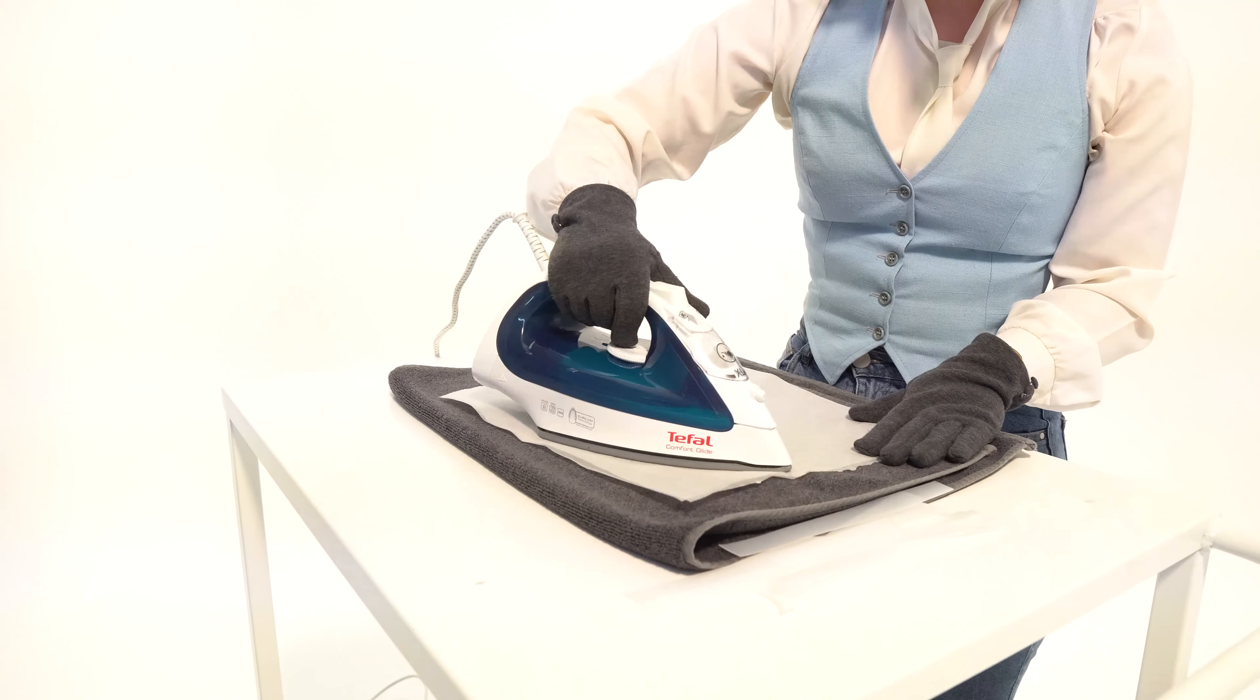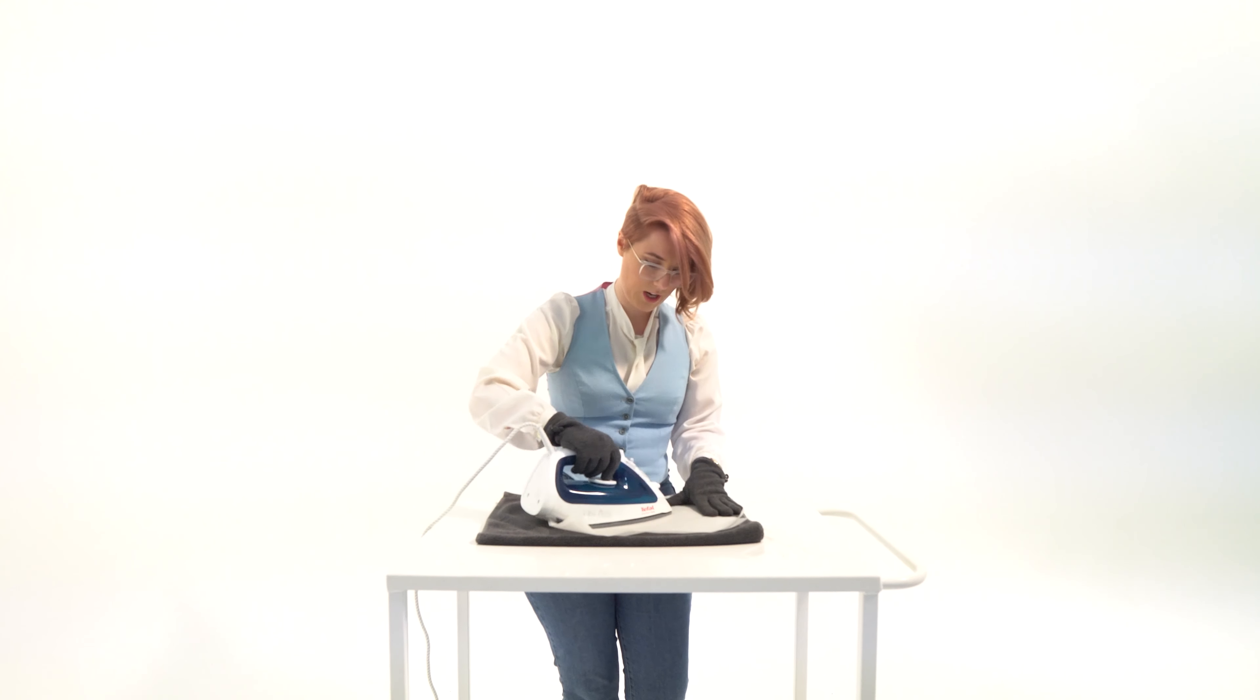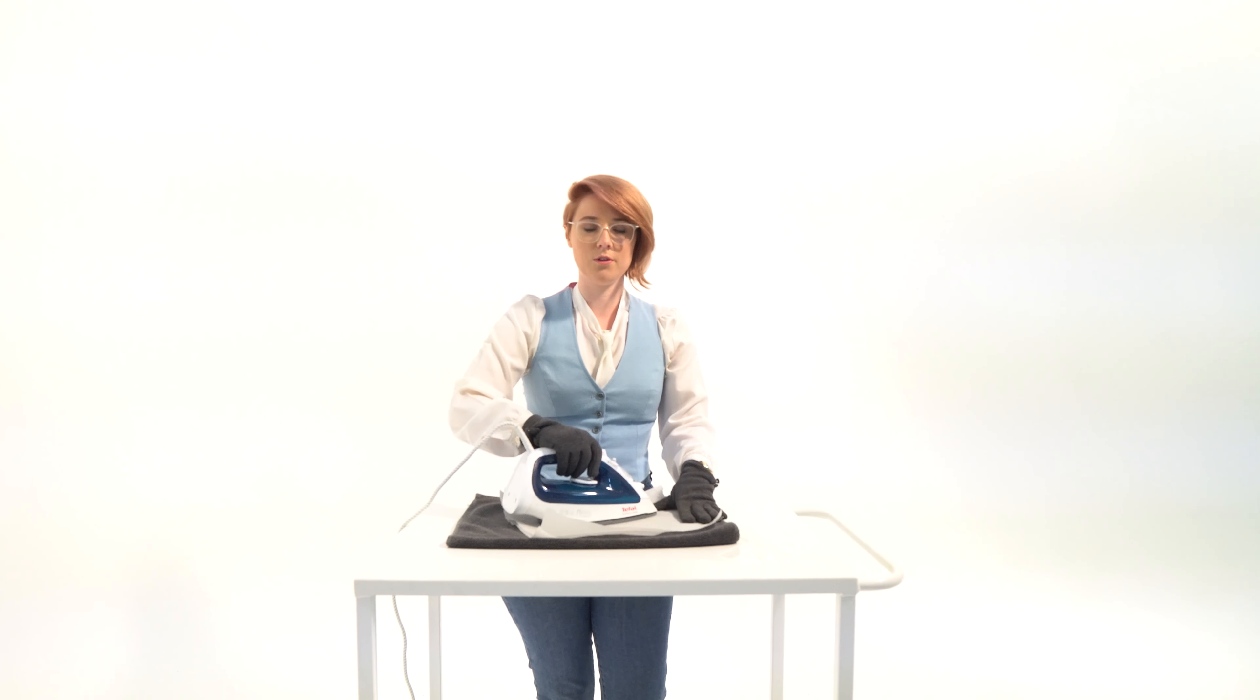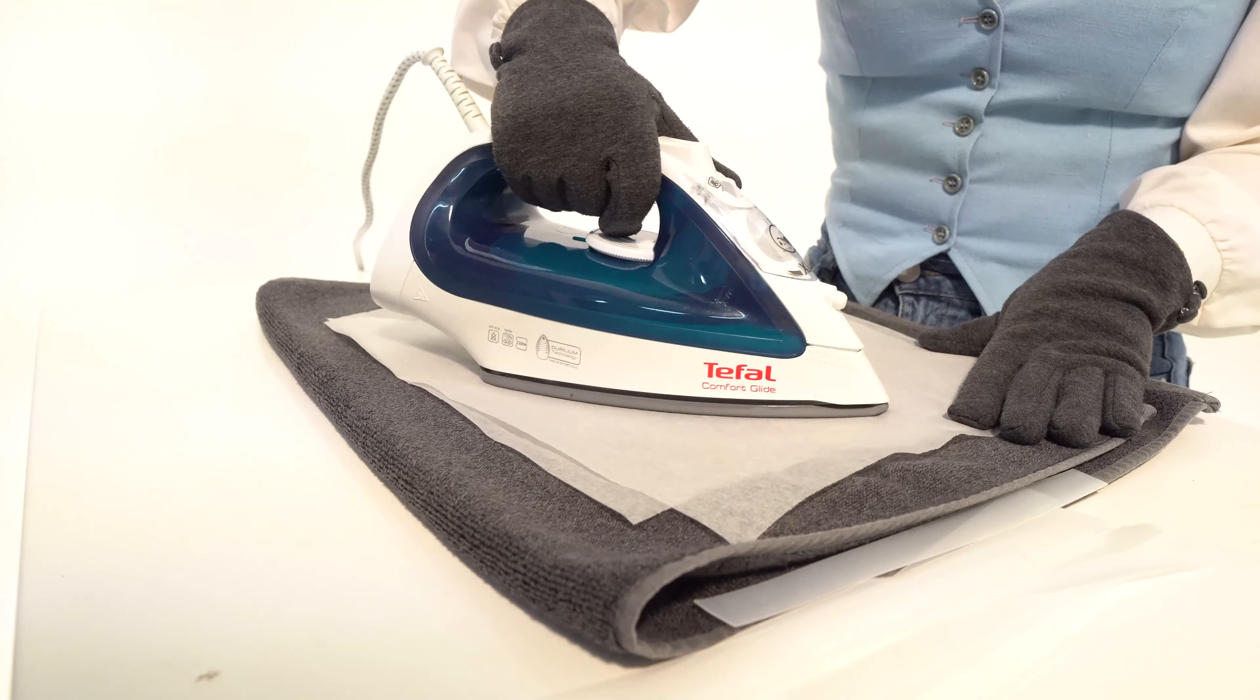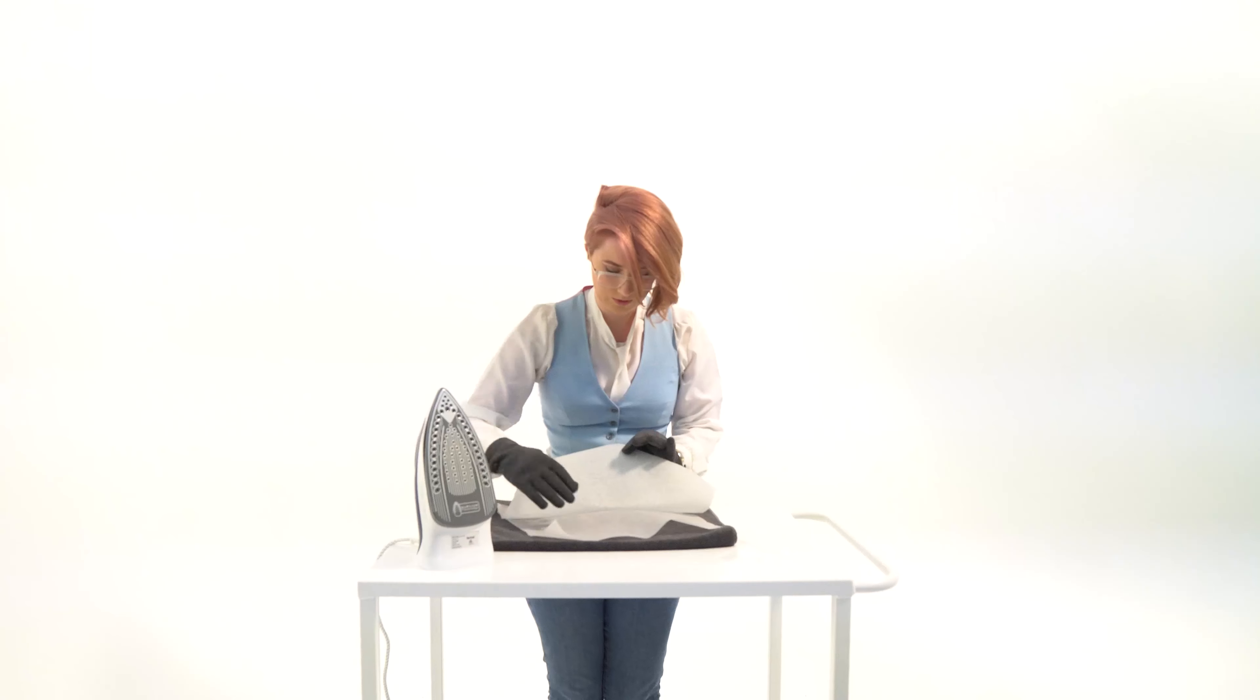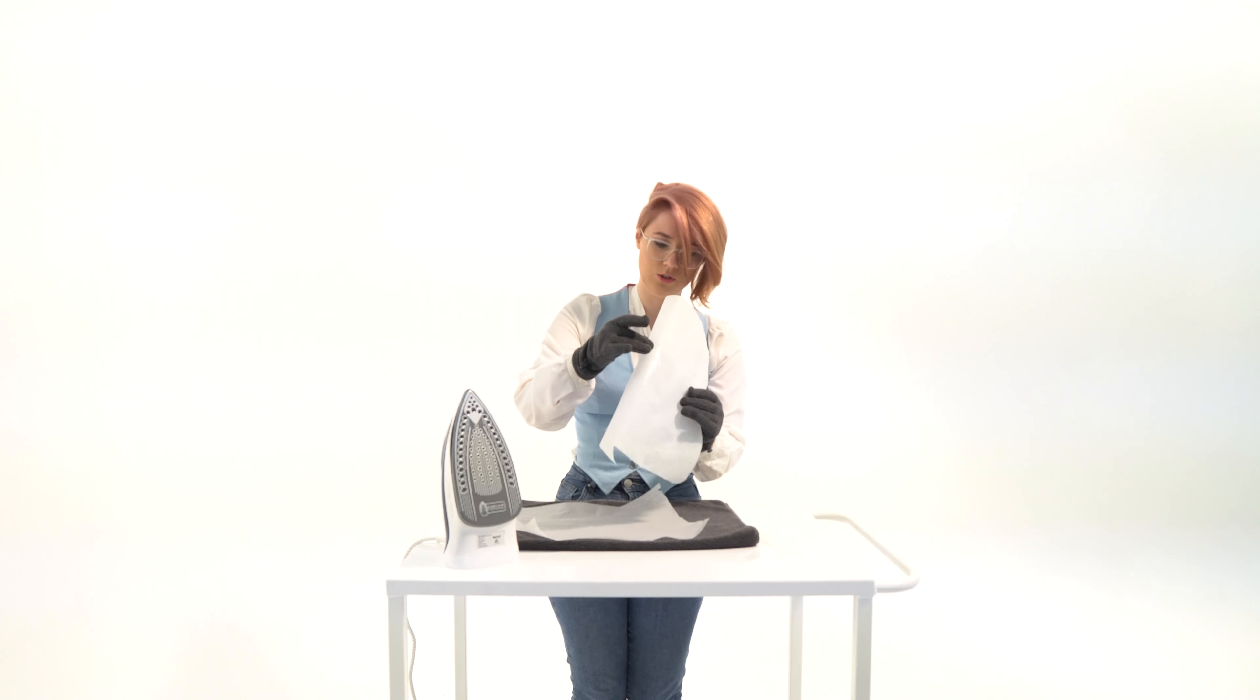Okay so I've got my plastic here sandwiched between my baking paper and then I just run the iron over it. As I run the iron over, there are a couple things that will happen. The baking paper will begin to move a little bit less and the plastic will start becoming more translucent, so you know when it's gotten really soft when it's completely translucent. So what I like to do is get it quite translucent all the way, and then when I pick it up you can sort of see it's really attached to the baking paper. Now if I try and play with it at this stage it's so soft it's quite hard to form and it will begin to stretch a little bit.